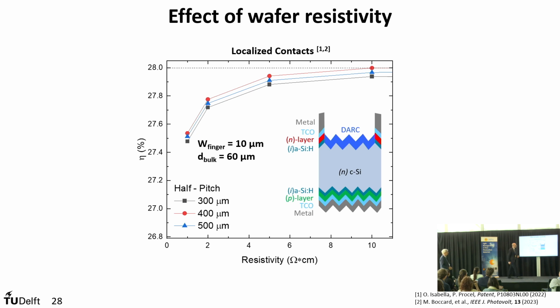In general, you can use any dielectric that can give a good passivation with respect to silicon. Could be also silicon oxide, but then it becomes too thick, then optically you have to do other tricks to do anti-reflective effect. So in our case, the best material so far is just a plain hydrogenated silicon nitride.